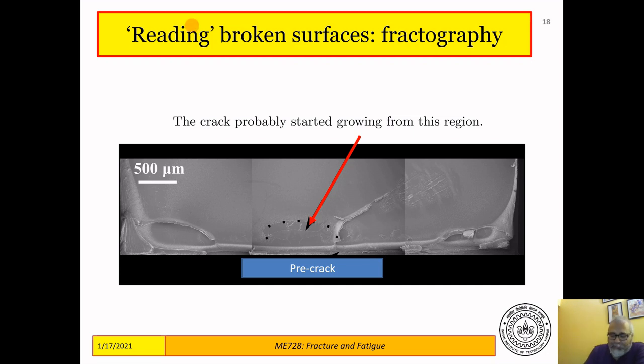So this is a sample. This is from our own work. This is a sample which from the side view looked like this. So it was a rectangular block of material with a crack here. This crack was put in deliberately, and this was loaded with two forces in this manner. And this crack propagated and broke the whole structure into two pieces, and then you are looking at one piece from this direction. And here is this pre-crack that you had. This is the initial crack that you had, which is this, right?